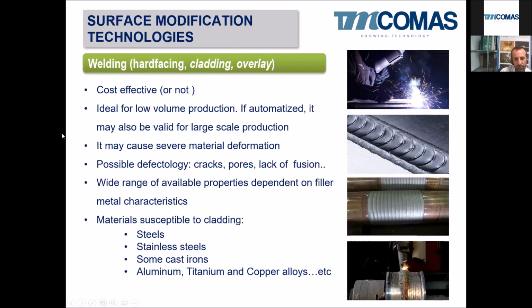Apart from that, possible defectology: cracks, pores, lack of fusion. I am not saying that all the welds, all the techniques, all the welders are creating defects, but it's a technology that can create defects. Everyone knows that, so we have to take it into account. Wide range of available properties depending on filler metal. That's a very important point of welding. There are hundreds of different consumables to apply on the materials to modify surface and wear properties. So there's plenty to choose.